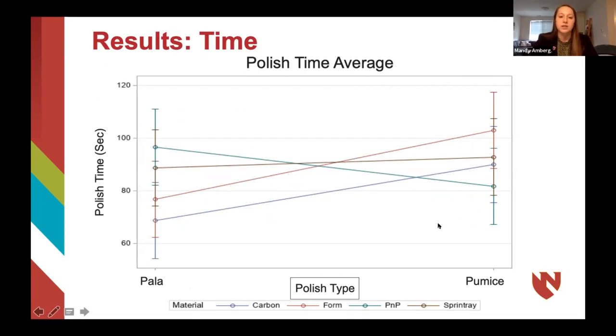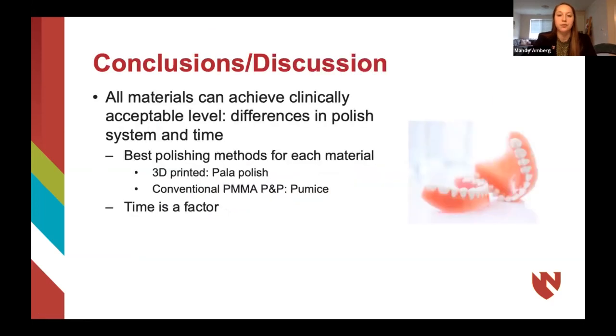Okay, we also found that there's a significant interaction between the material and polish type in terms of the amount of time spent polishing the material. When looking at this graph, we can see that all 3D printed materials took less time on average to polish with polish paste than with pumice, while the conventional materials take the least time out of all materials to polish with pumice, but the most time out of all materials to polish with polish paste.